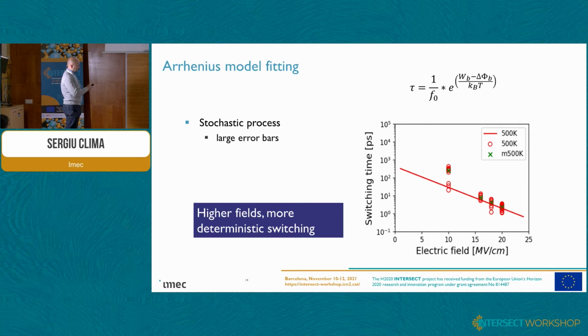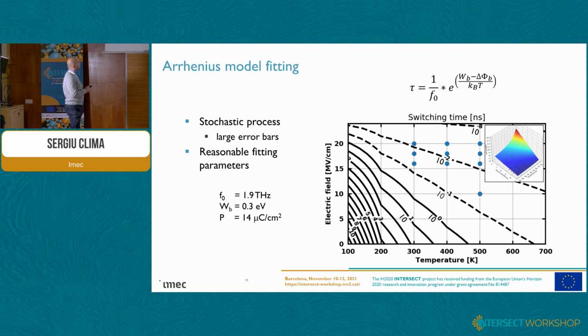Nevertheless, we can try to fit the switching of these ferroelectric materials to an Arrhenius behavior, and that's what I've done on this chart. So what you see here are the high field and high temperature data points shown as blue dots, and then we could fit an Arrhenius surface, shown with iso-lines for a power of 10 in nanoseconds.